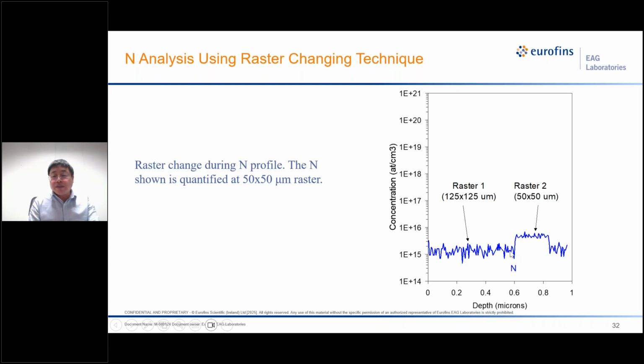Here it shows the SIMS result for the raster change. This quantification is based on the smaller raster, and if we use the equation from the previous slides, we can calculate the nitrogen concentration. In this case, it's about 3.5E15. This method was tested under different nitrogen backgrounds, for example 2E15, 5E15, even 1E16, and the raster change method result is always consistent, within 20%. I also want to point out that the raster change method requires constant doping level. If the doping level is not constant, you cannot use the raster change method.